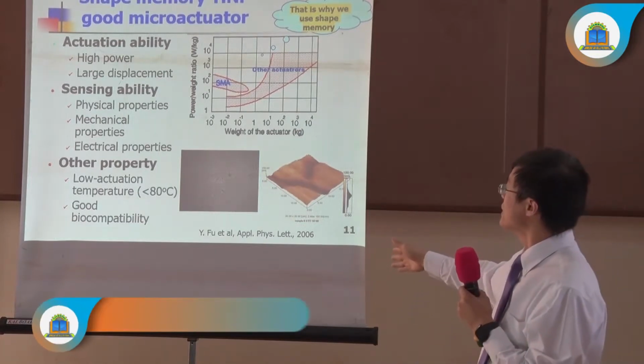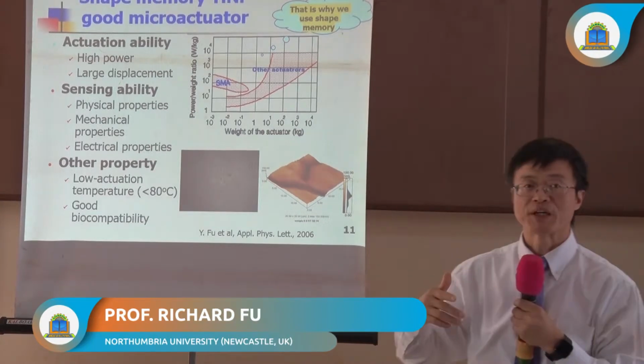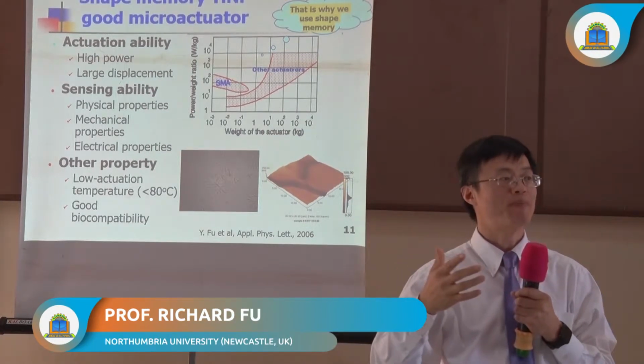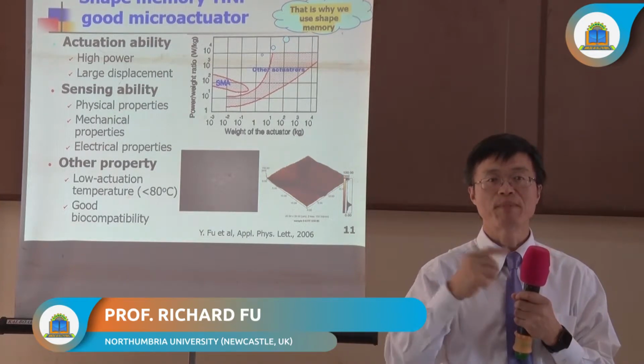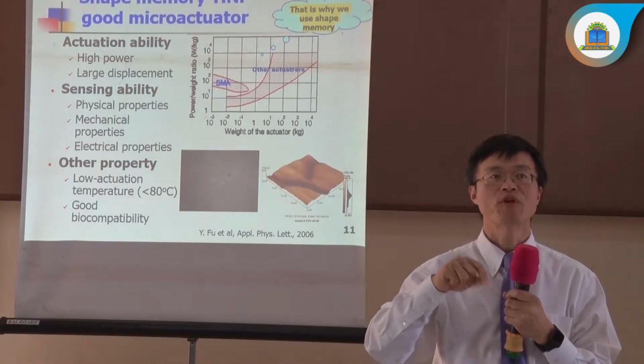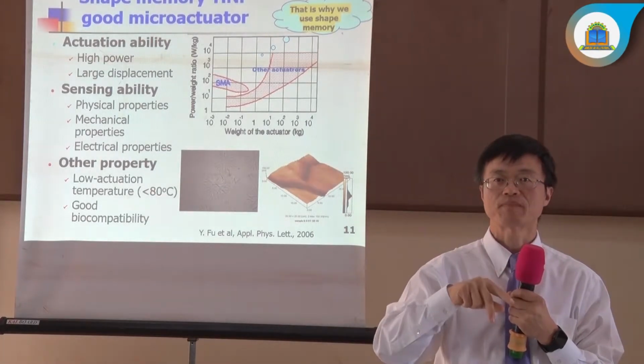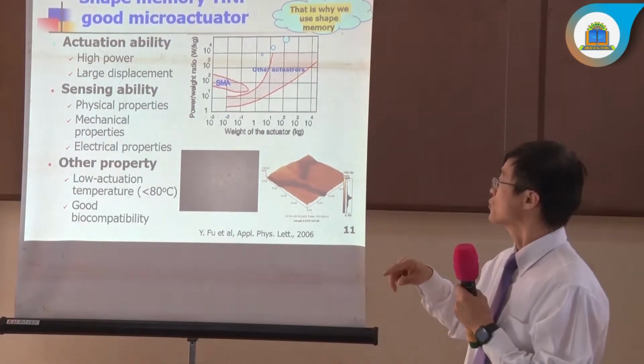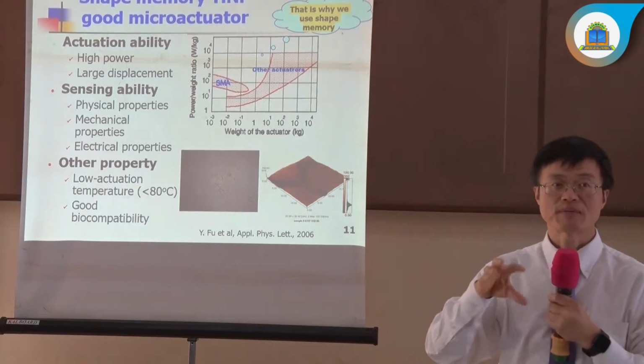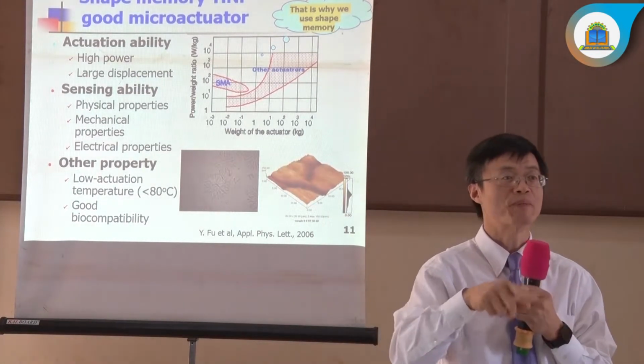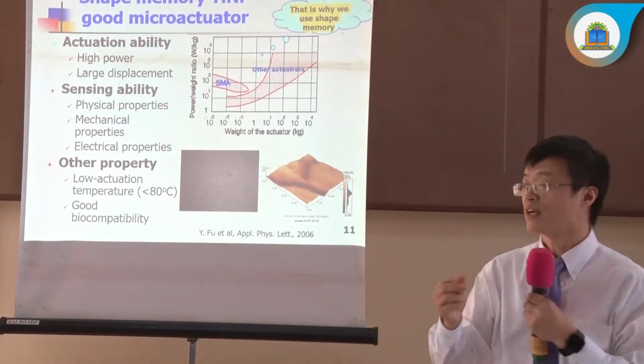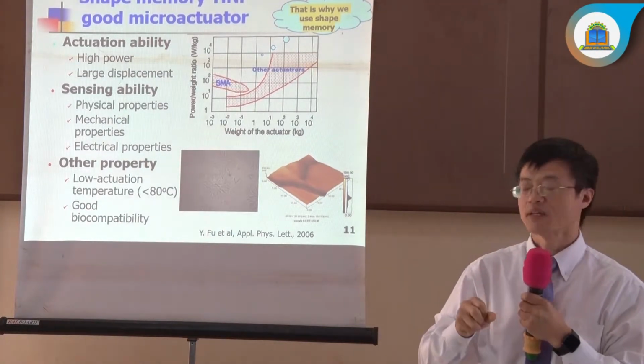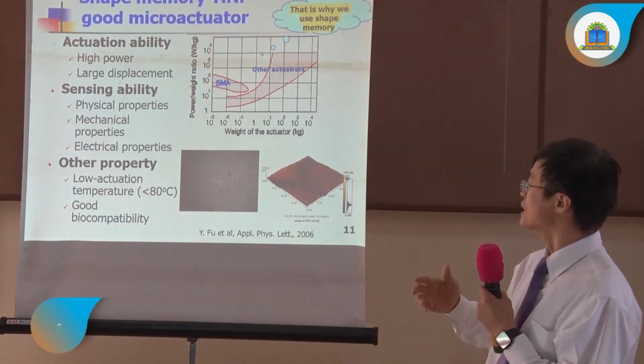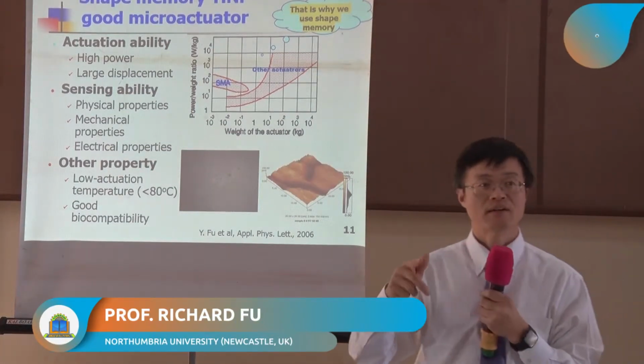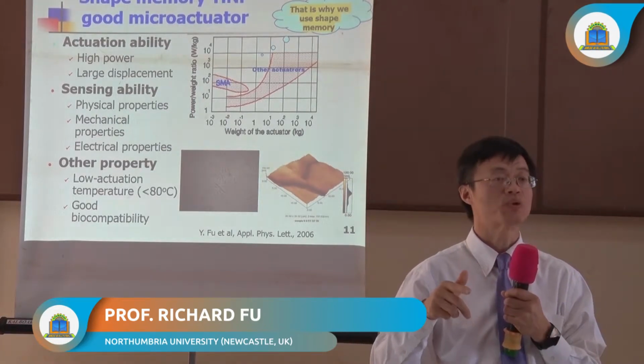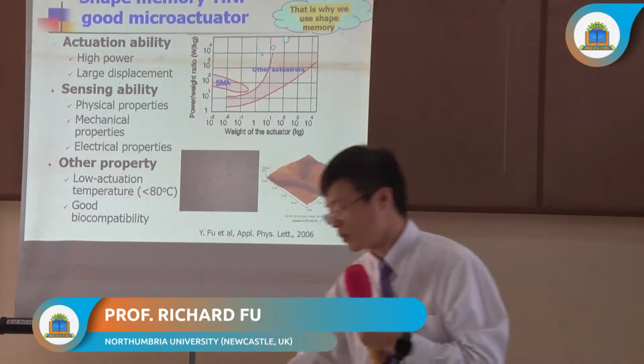So shape memory alloy, why we need to use it for the actuation? Because among all the principles for actuation, shape memory alloy, for the same weight or same volume, will give you the largest force or largest power. So that means if you have the same weight or same volume of the material, shape memory alloy will give the best actuation performance. Force and pressure is very large. Along with it, other properties will also change. So that means you can also use it for sensor actuation, for both.